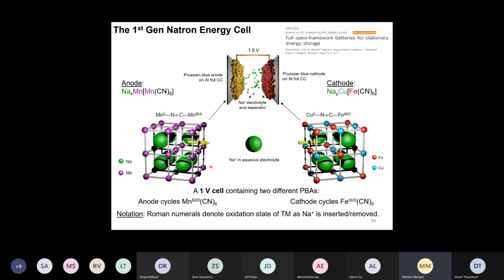So let's look at what Natron did with this material. So this is their first generation cell, and it's also described in the paper that Jeff mentioned initially. So this is a 1 volt cell, and it uses 2 different versions of these Prussian blues. So 2 different Prussian blue analogs on anode and cathode. And they are both coated on aluminum current collectors. And the electrolyte is a sodium ion containing electrolyte, they say. And there's a separator, of course, also in there, which is not drawn here.